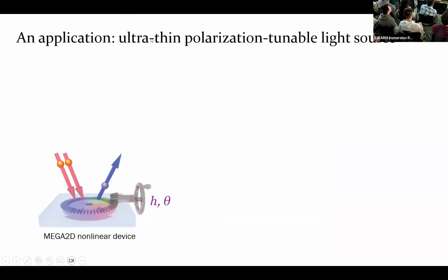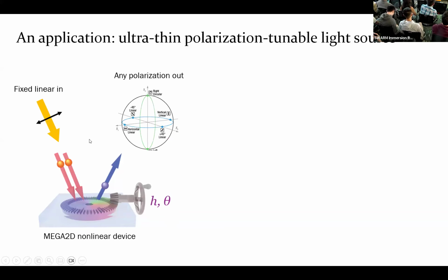So one potential application that we think we have for this system is to build a polarization-tunable light source. The idea is that we have a tunable system with some knobs on it, right? Just think of some gears that you can rotate. And now if we put in a fixed polarization light, like a linearly polarized light, the output can actually be in arbitrary polarization. An arbitrary polarization is usually represented on the so-called Poincare sphere, where the endpoints of this sphere represent either linearly polarized light, or circularly polarized light on the top and the bottom of this sphere. Okay.